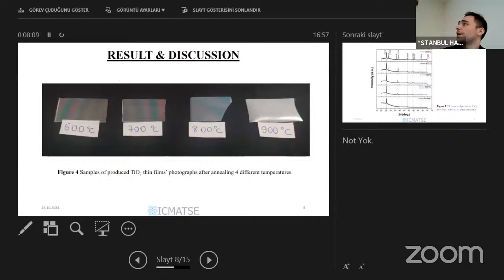These are our samples after annealing at 4 different temperatures. You can see that at 900 degrees there is a different surface than the others, so we will talk about this in the XRD and AFM structure analysis.